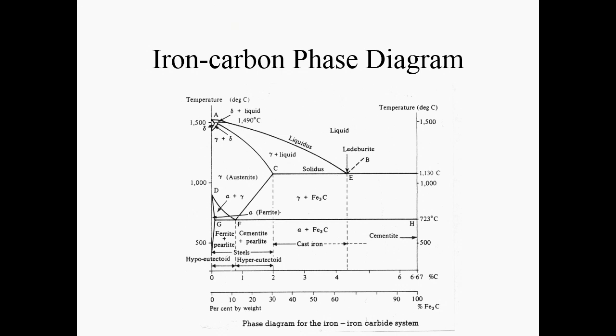If I had an alloy with 1% carbon at 1000 degrees C, we'd be here, and we're in a solid phase range from a material called austenite, which is iron with a face-centered cubic crystal structure that can dissolve carbon up to 2%. If I had 0.1% carbon at 500 degrees C, we're in here, and we're in this range where it says ferrite and pearlite. Ferrite is body-centered cubic iron. It's what you get at low temperatures, and that can dissolve, that's this alpha in here, only about 0.04% carbon.